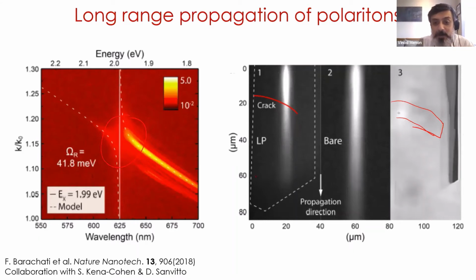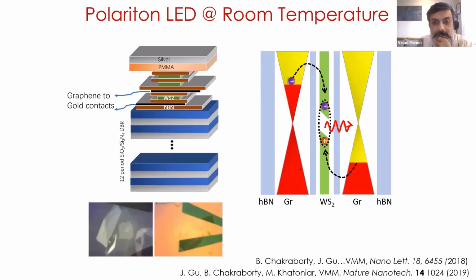It's able to propagate up to about 60 microns in this case without getting disrupted, because it has inherited the property of the photon, and hence it doesn't see these cracks in the system. This was work we had done in collaboration with Stefan Kena-Cohen and Daniel Sanvitto's groups, where we showed this long-range propagation. More recently, we got into the business of asking the question, can we make these systems electrically driven?